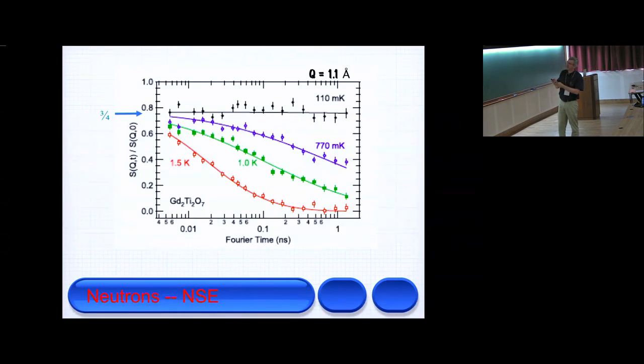And our instruments don't allow us to probe this at the moment. But what can we get from this? Well, we see that where it does saturate is 3/4, and those models were all 3 spins static and 1 spin dynamic. So that kind of agrees there. And what we're seeing here must be the relaxation processes in the 3 that eventually become static. And the one that's dynamic must be very fast inside this range. And so this is the fastest neutron scattering technique. It looks at things normally in polymer physics where it's very floppy, so slow dynamics. But there's a lot of dynamics that are outside our window.